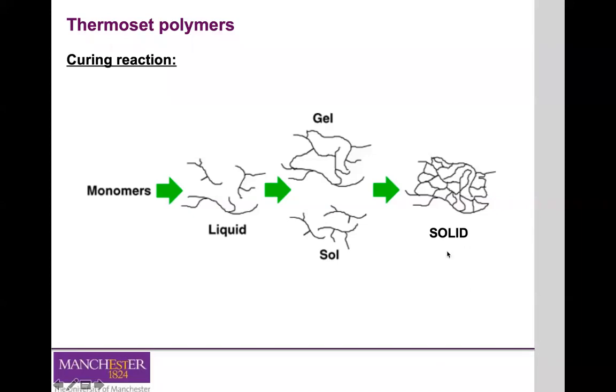And this goes through different stages. In the first stage of polymerization, these monomers will react with the photoinitiators, and they will promote the cross-linking between the monomers and between different chains of monomers that are formed. The first stage of polymerization is called gelation. And at this stage, you have two phases. One phase that is completely chemically cross-linked, that is called the gel phase. And you have another phase that has not yet reacted with photoinitiators, that has not yet reticulated, and is called the sol phase.